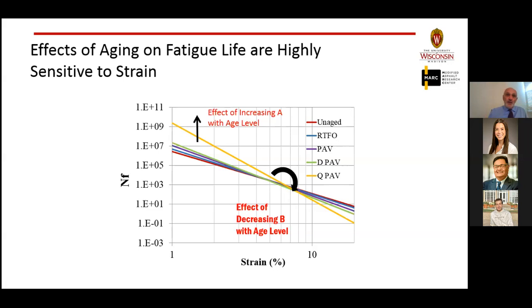One of our DOT engineers, when he saw the data of better fatigue, said, oh, all I have to do then is wait for the pavement to get stronger. Is that what you're telling me? Of course, the answer is no. I think we were misled by testing in the conditions that give you the impression that the fatigue is getting better, while in fact there is a rotation in the slope of the line of the fatigue that will clarify the effect of aging is not as good.